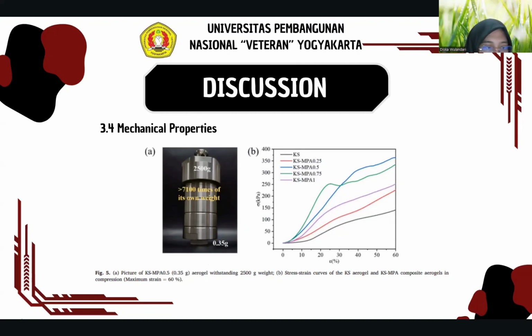initial linear deformation, plastic deformation and densification. The maximum compressive strength of aerogel KS was 141.5 kilopascal, with KS MPA 0.5 saw a significant increase to 364.9 kilopascal.